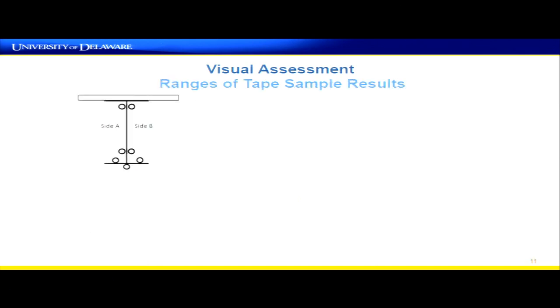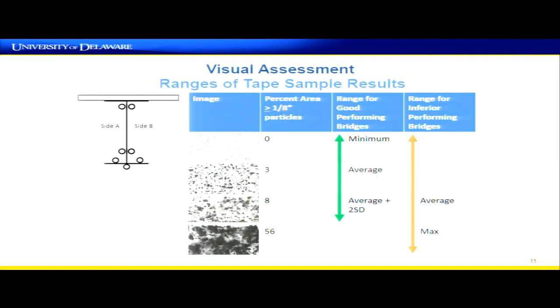Another thing we need to understand about this data, though, is that these samples come from several different locations on the girder. So those circles are the cross sections where the data is coming from. It's also coming from different girders, different longitudinal positions along the length of the girder. And there's a gradient in what those tape samples look like at different locations. So it's probably no surprise, for example, that up here at the top of the web, we have less corrosion than at the bottom.